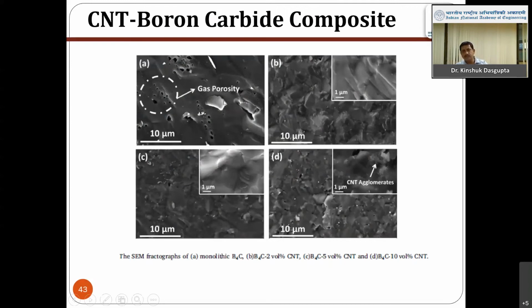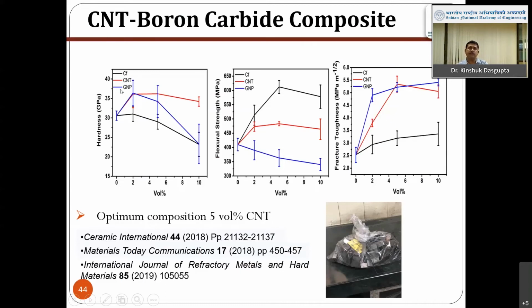So this is without carbon nanotube, and we could see some kind of porosity is present. And when we go on adding 2 volume percent, then 5 volume percent, then 10 volume percent, we could get the full density, but at higher volume percent you get the agglomeration. And if we check the properties, what happens? We have added not only carbon nanotube, also other carbon-based materials like carbon fiber and graphene nanoparticle. Why? I am telling you, carbon nanotube is considered a one-dimensional material, graphene nanoparticle is a two-dimensional material, and carbon fiber is a macro material, in the macro dimension, not the nano. So how does their addition affect the property of boron carbide? Here you can see that the hardness, which is very important for boron carbide, generally improves initially, and it improves due to the improvement of basically the porosity, nothing else.